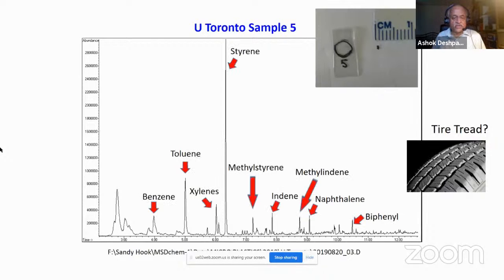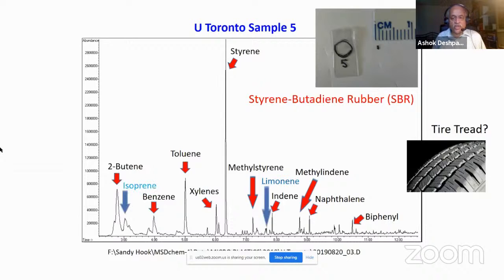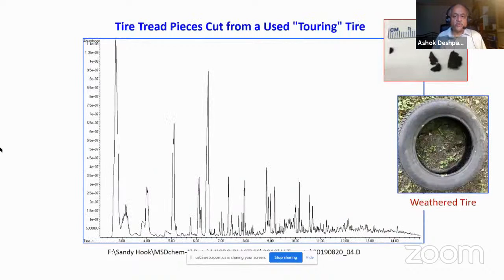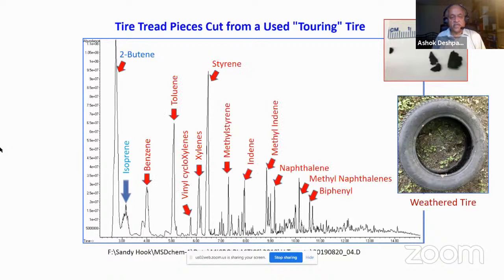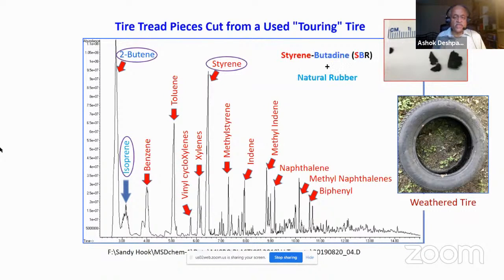In this sample, we found styrene and bunch of other compounds. We found butene, so we call it styrene butadiene rubber. It also contained isoprene and limonene, which was indicative of natural rubber. So it will be SBR NR rubber in the sample. In order to confirm our analysis, I found a tire in my backyard. So I cut some pieces and ran the GCMS analysis using pyrolysis. And it has butene, it had isoprene, it contains styrene and other aromatic compounds like we saw before. So we call it styrene butadiene plus natural rubber. I could not find the limonene peak in this particular pyrogram.